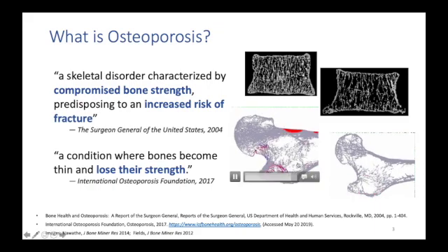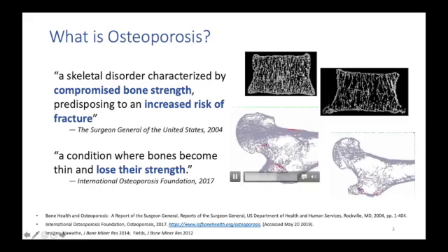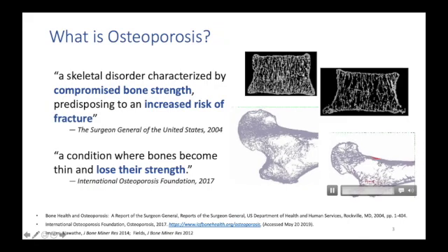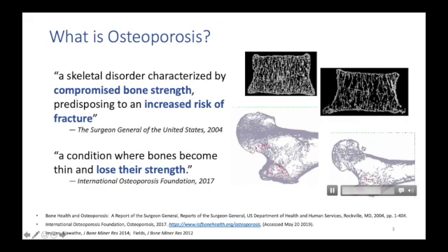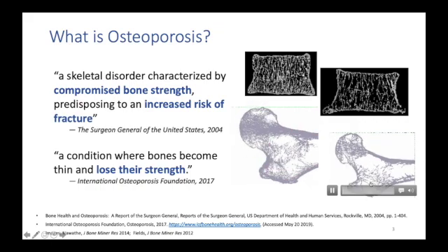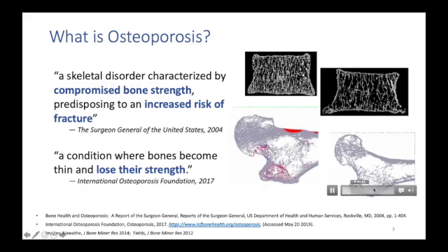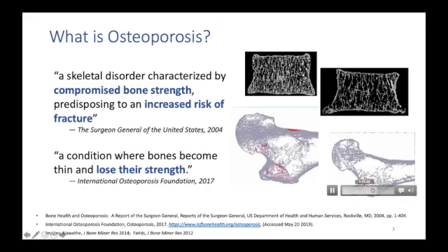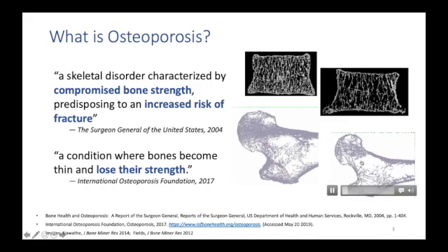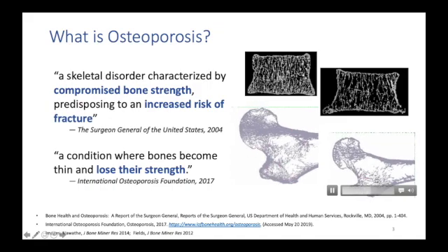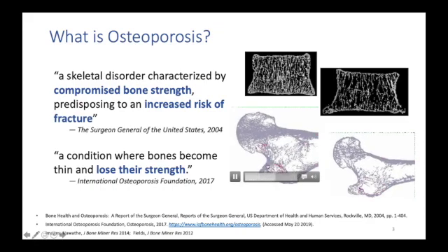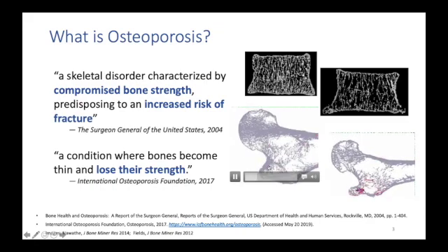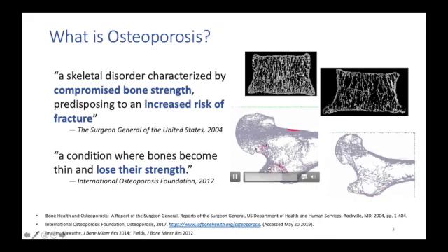But what you can see from the failure regions is, if you look on the right femur, there's not that much coloring of the tissue. We're simulating these up to the point where the femur is just about to break. So when the whole femur has failed, not much tissue has actually internally failed for the bone on the right, which turns out is a very weak bone. And the bone on the left, which is a much stronger bone, requires a lot more failure of tissue. And that concept is one of structural redundancy.